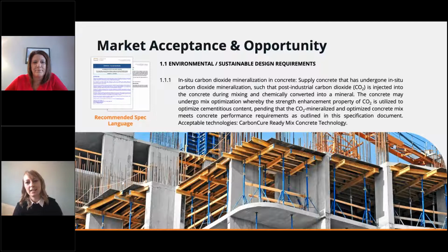Perfect. Thanks, Shannon. I've been following the questions that have been coming in while you were speaking, and I'll address one of them right now because it leads into this. So CarbonCure, on average, reduces about 25 pounds of CO2 per cubic yard of concrete. This really depends on the concrete mix. It can vary quite a bit based on the amount of mix optimization that has been achieved.